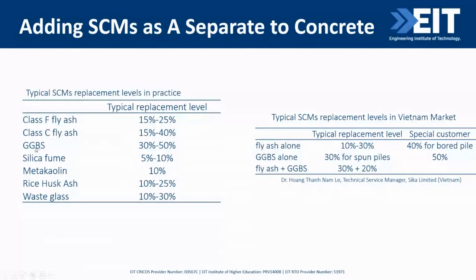And then next, GGBS. GGBS commonly constitutes between 30 to 50% of the cementitious materials in the mixture when used in general purpose concrete. Some slag concretes may have a slag component of say 70% or more of the cementitious materials for applications such as mass concrete and marine environments. And then silica fume is typically used in amounts between 5 to 10% by mass of the total cementitious materials. It is used in applications where a high degree of impermeability is needed, and also in high strength, high performance concrete.